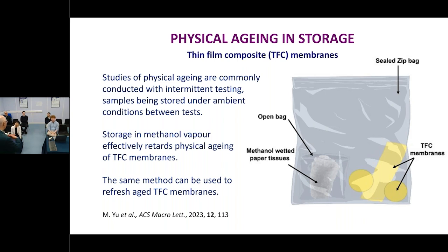but it's hard to do that often with a thin-film composite because you can then get delamination of the different layers. But we can get the same effect actually just by storing in the methanol vapor. So a very simple way of keeping this in the methanol vapor can actually retard some of those aging effects or refreshen them.